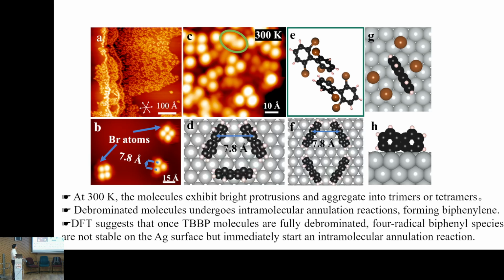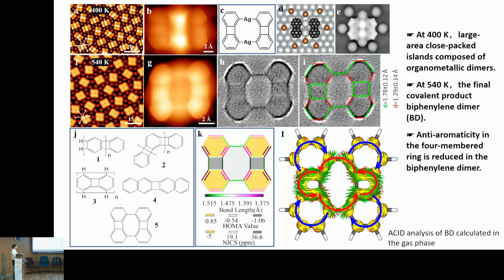This means that when this is debrominated, DFT calculations show that the debrominated molecule first undergoes an intramolecular cyclization reaction once these radicals form, and then immediately the molecule is bent and forms this four-membered ring here, and the rest two just stay on the surface. Then when you increase the temperature to 400 Kelvin, you still have this carbon-silver peak in the XPS. That means you have the organometallic species. You can see from the STM that you have this broad protrusion, which is assigned to the adsorbed silver atom here. These mimic the DFT calculated results, which is very consistent with what we observed.